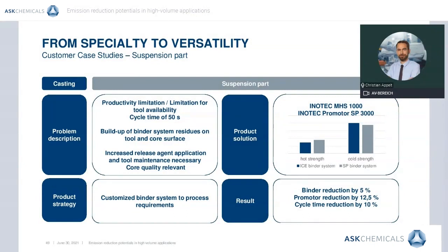The solution here is to customize the binder system to the process by providing a binder system with an adjusted strength profile. Inorganic binder systems for suspension part cores need an adjusted strength profile in comparison to cores for cylinder head or crankcases. Higher immediate strengths are necessary, lower final strengths are acceptable. As a result, the components of the binder systems could be reduced, enabling a cycle time reduction by 10%.